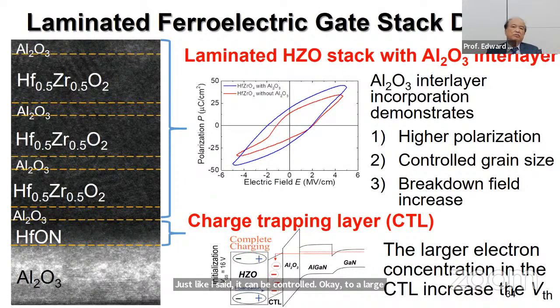And also for the charge trapping layer, we use hafnium oxynitride because that will have a larger electron concentration compared to hafnium oxide. And this shows that the leakage is really reduced using this kind of laminated structure. With the aluminum oxide interlayer incorporation, you can see that it reduces the leakage current and gives a high breakdown voltage.